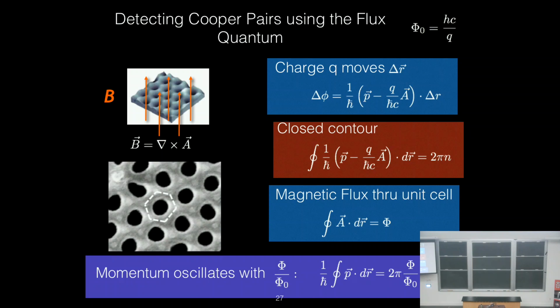What that means is a charged particle in this film gets a phase change due to the magnetic field. And it turns out that that phase change is periodic in magnetic field because of the holes. If I put on a magnetic field such that there's one flux quantum per hole, the system behaves as though it has no flux quanta, or 2 flux quanta, or 3. There's a flux periodic behavior in the system if you have this change in momentum. There's something called the Aharonov-Bohm effect, and this is definitely what this effect is due to.